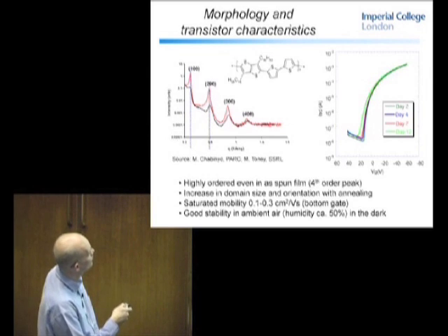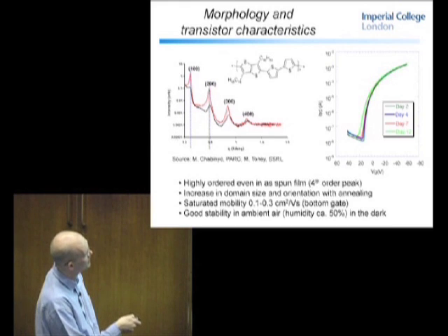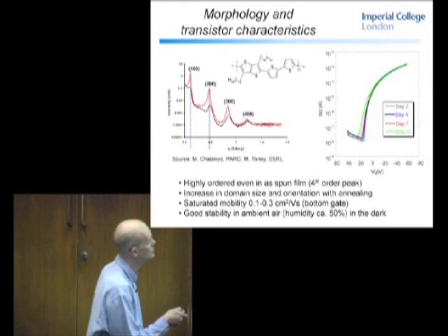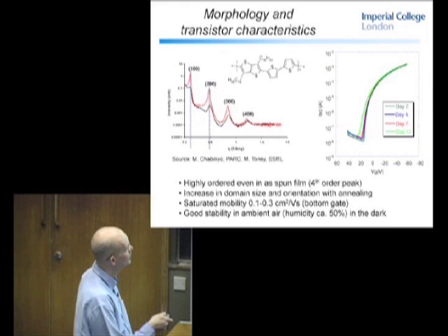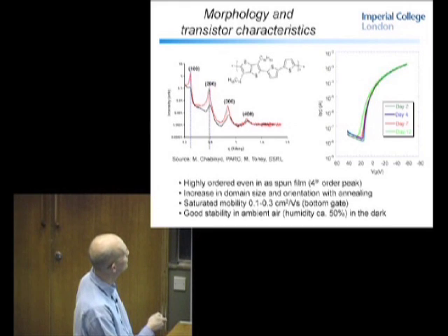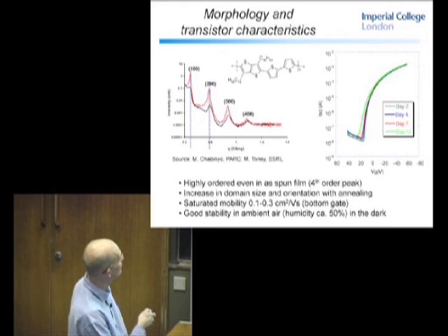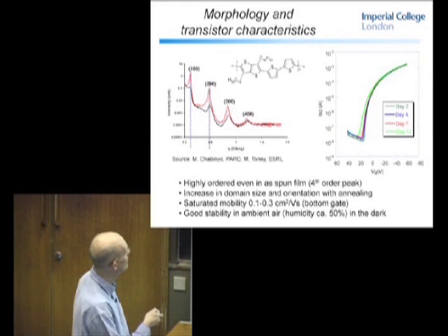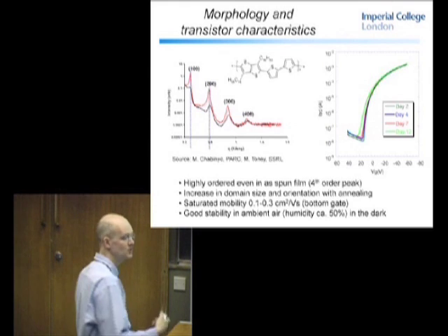But eventually we found one where we had, in ambient conditions, almost completely reproducible transfer characteristics up to, we could have kept on going, I guess, but at this point we sort of proved our point, that it was very, very stable. And again, if we look at specular X-ray diffraction, you see these very sharp peaks. You actually even see them from an as-spun film.